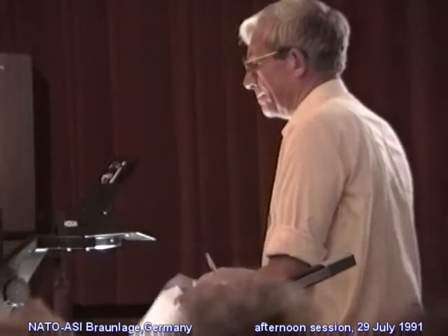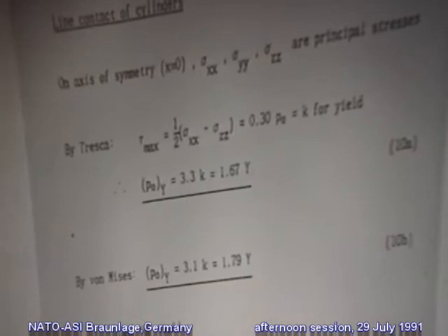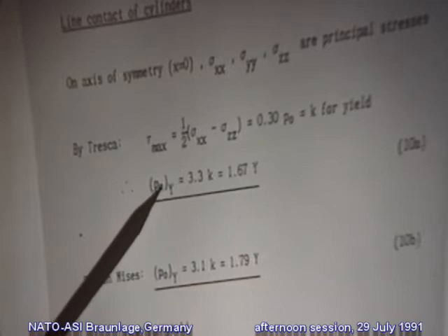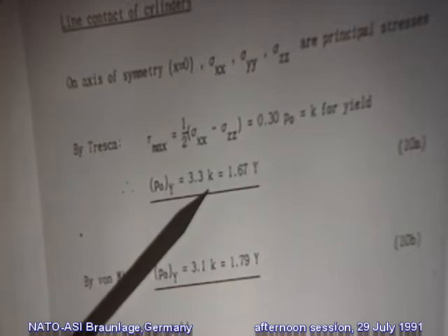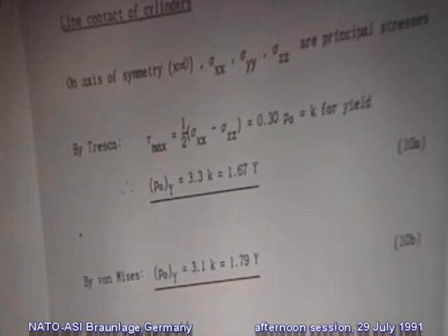And then if one applies those yield criteria to the stresses beneath the contact, and uses the stress distributions which we just derived, then we can get expressions for the maximum pressure, p naught, at the yield point, which I denoted by p naught suffix y, in terms of either the yield stress in simple shear, k, or the yield stress in tension denoted by capital Y. And you'll see that the differences between the two yield criteria are not great, either for a line contact or for a circular point contact.